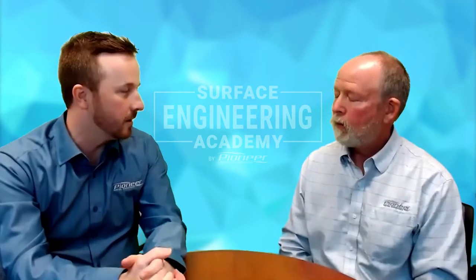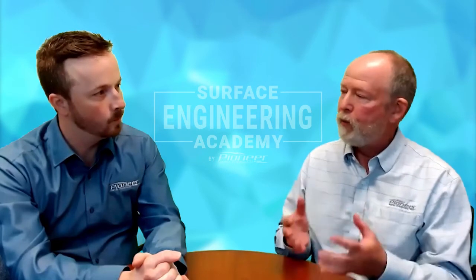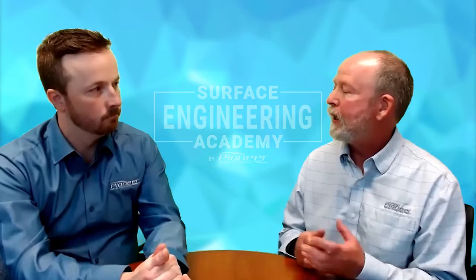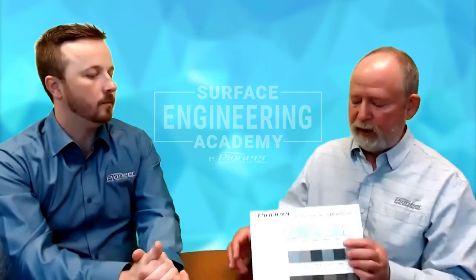There are a number of other factors — we won't get to them all today. Regarding thickness, dye exposure, and alloy: our customers pick the type of aluminum for the purpose of making the part. They might use a casting or an alloy with high strength. All these different aluminums anodize differently — at different thicknesses and different coating densities, so the porosity varies. Even standard anodizing will have various background hues because of the other metals in the aluminum. As we go thicker and denser, it discolors more, and when we impregnate the coating with dyes, this background color can have a dramatic impact.